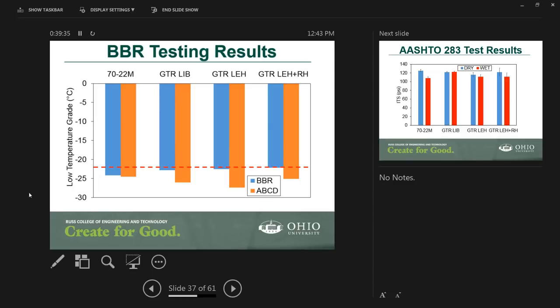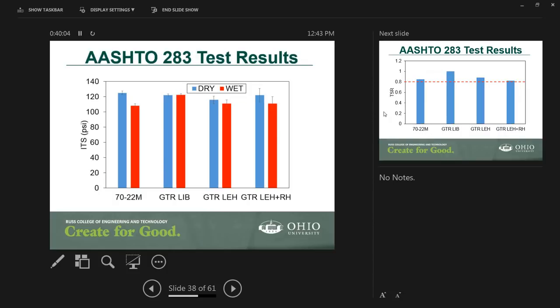For example, for the 70 minus 22, you can see that the results were very similar. For the GTR, there were differences. Because the percentage of the modifier here is significant, your BBR, I would say the boundary condition as well as other things with the test itself, might have a problem in evaluating the low temperature of that modified binder. So going to the mixes results, the ITS.